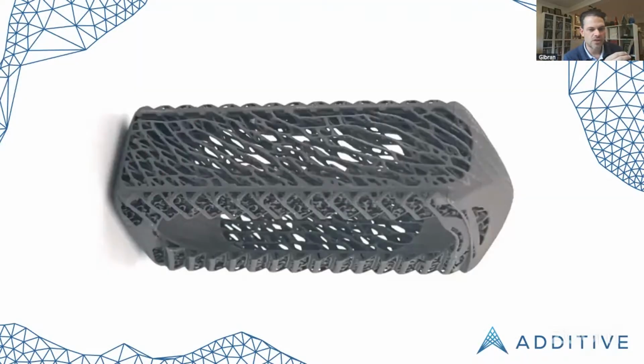So this is a worst case lumbar cage for a lateral approach. Now, there would never be a cage this big used clinically. This is when we have worst case testing. What that means is we can never make anything bigger than this, and we do all our tests to this. I think it's 16 mil high, 65 long, 25 wide cage. We test and validate this worst case. So anything smaller than that is going to perform better as far as mechanical and structural testing.